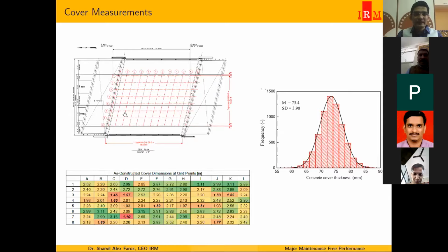So we made a grid marking on this, and we measured the concrete cover at each and every location, and we created a histogram. You see here, the histogram we have created. We found the average value to be 73. Now, what was provided should be 75 mm, but because of construction errors, the cover was just 73 mm, and there was some standard deviation also. So exactly 73 mm was also not possible. It ranged between 60 mm and 80 mm.